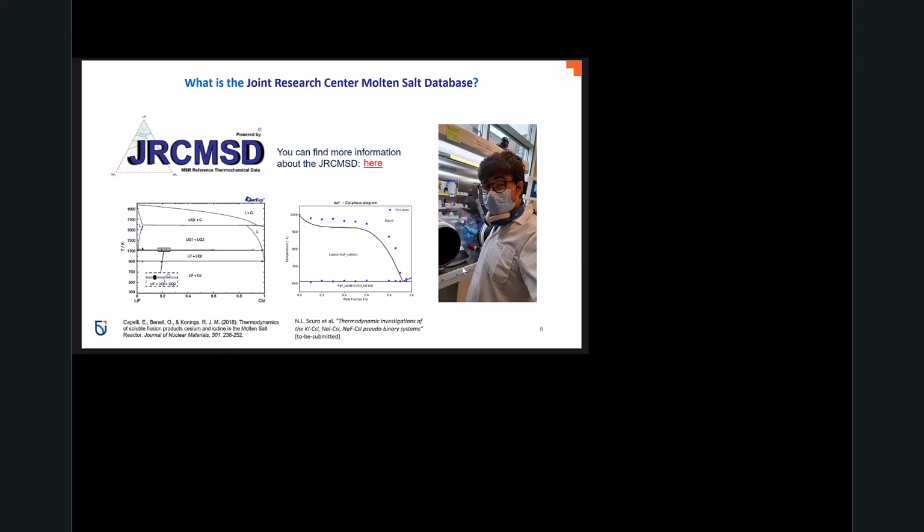And we do that in a laboratory using a glove box. This is me at Ontario Tech University, where we perform several different mixtures of those salts, put them into a machine, and analyze when they are going to melt. Then we can create these phase diagrams to better understand when certain species will melt or solidify, or when we have a mixture of several different phases.